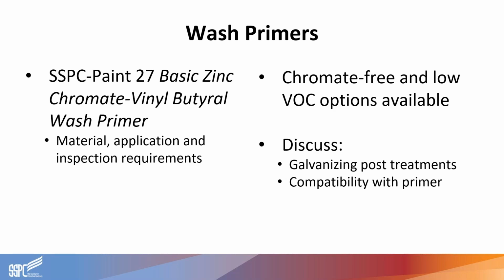A wash primer or a self-etching primer, this is where we look at a metal conditioner to neutralize surface oxides and hydroxides, but it'll also etch the galvanized surface to give you a surface that's suitable for painting. SSPC Paint 27 addresses more of the material application and inspection of wash primers, and there are other types of options to meet environmental requirements as well.